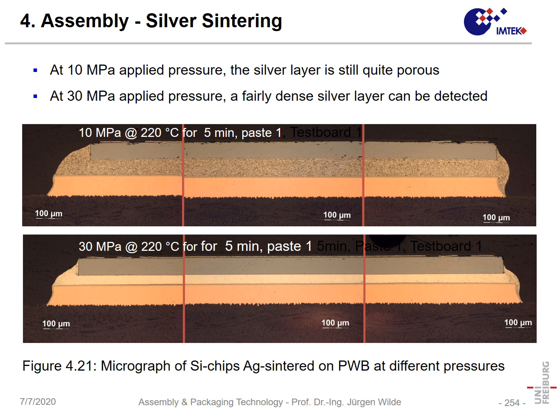Now the result, for instance, to show you what the difference is with respect to pressure or also with respect to time. You can even see the individual powder particles and the porosity in between, so that is sintered only partly. And if you put on more pressure, you give more bonding energy to the process, and that means you have a very dense connection. And here that is just pure silver, and that silver is very stable. Also, silver is the material with the best thermal conductivity you can have from the metals, and in that way you can have an ideal connection for IGBT